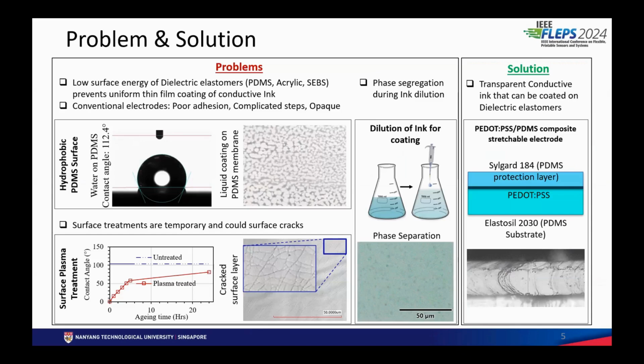To make a transparent acoustic absorber in a more scalable way, we need to make sure all the electrodes are transparent as well. One of the big problems is that there are very few stretchable transparent electrodes. Some can be made by formation of micro wrinkles, but they will not be that transparent because they will diffuse light. There are some sources of nanowires, but the process of putting nanowires on very low surface energy elastomers like PDMS, acrylic, or SEBS is quite tough. The most straightforward approach would be to use some form of ink that can be directly coated on low surface energy dielectric elastomers. But if you coat an aqueous-based ink on a low surface energy elastomer material, it will form non-uniform patches, right? The connectivity and the overall coverage of the area would be very bad.